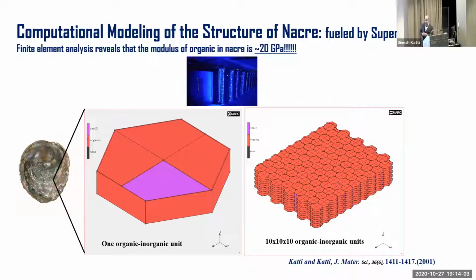At that time, we did not know what the elastic modulus of that organic phase, the 20 nanometer thick organic phase, was. And our simulation showed that the elastic modulus of this organic phase is about 20 gigapascals. Now, that number, 20 gigapascals, is about 1,000 times more than what we were expecting. The reason I'm saying 1,000 times more is that this organic mortar is made up of proteins, and bulk proteins have an elastic modulus of only 20 to 50 megapascals. That's 1,000 times less than this number.